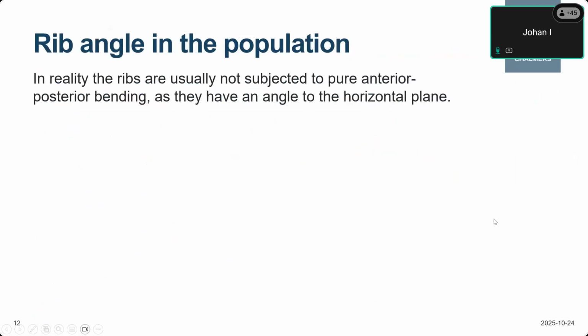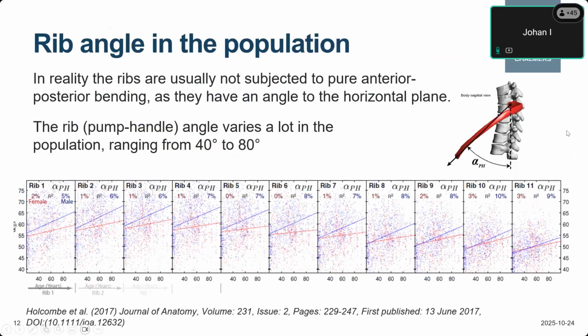But in reality, ribs are usually not subjected to pure anterior-posterior bending, as they have an angle to the horizontal plane. And here we can look at some data from Sven Holcomb, published 2017, where he measured in the population the pump handle angle. So that is the angle from the vertical plane to the plane of the rib. And we have that for rib 1 to rib 11. We can see that it varies a lot in the population, from around 40 degrees to 80 degrees. We can see that it varies from rib to rib, and we can see that we have some significant effect of age. Here, the blue are the males and red are the females.